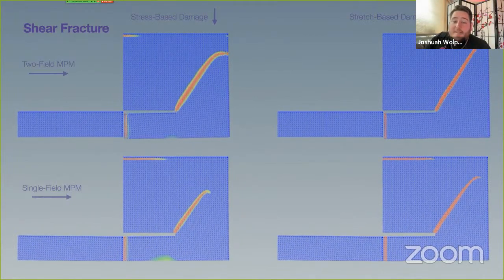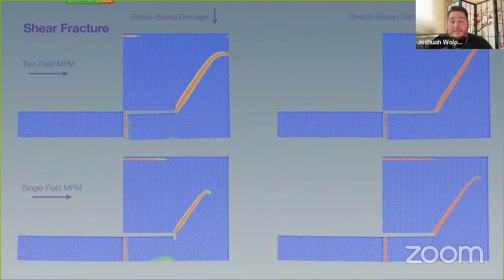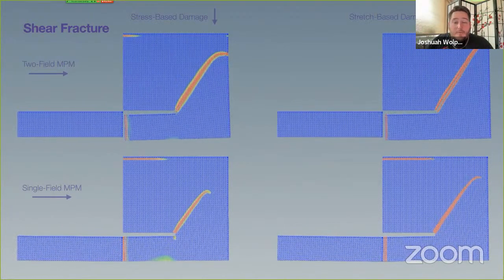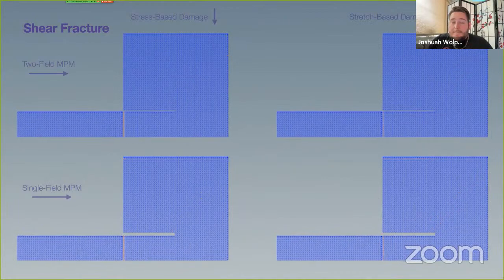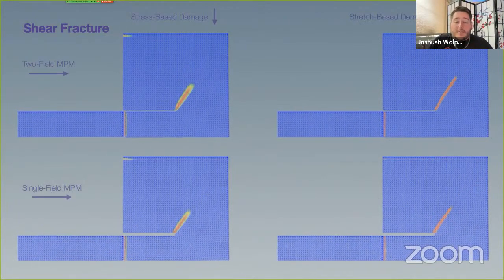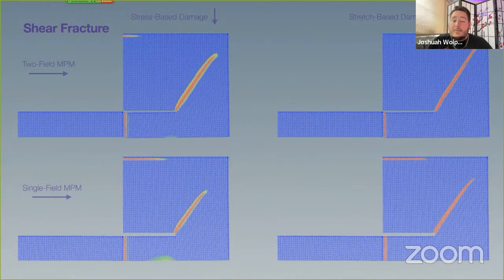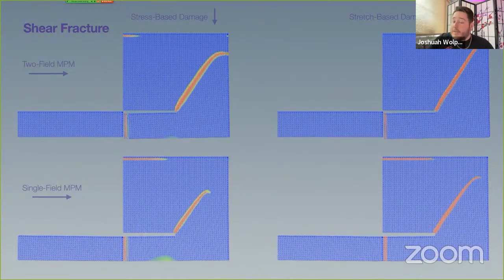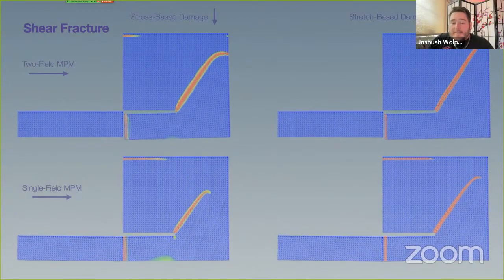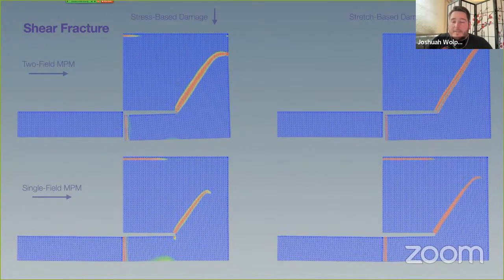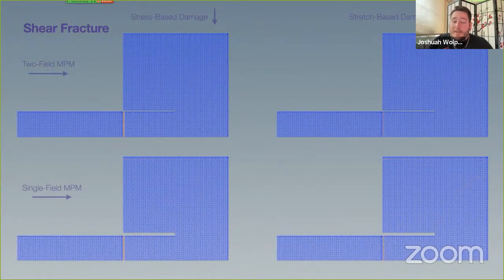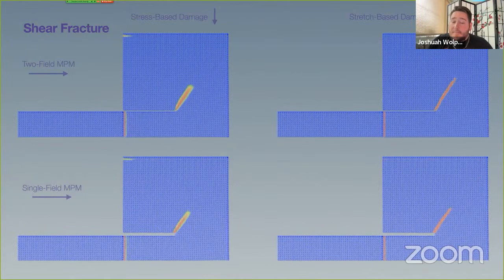In the top row, we simulate using damage gradient partition two-field MPM, whereas on the bottom row, we simulate using single-field MPM. And in the left column, we're using a critical stress-based damage model, and in the right column, we're using a new critical stretch-based damage model. So notice how the single field runs on the bottom show an accumulation of damage near the top left of the material where it's held in place by a boundary.